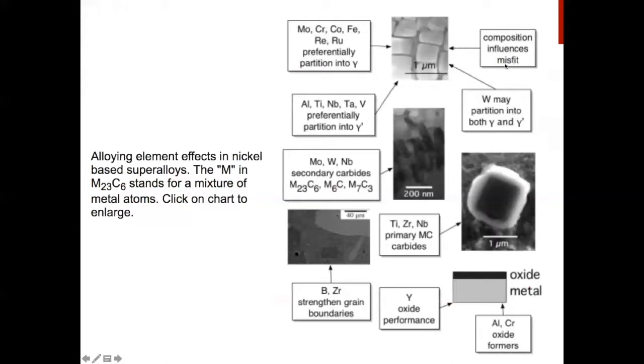Our composition strongly influences misfit. Tungsten can either partition into gamma or gamma prime, depending on what other elements are there, right? We have our gamma prime formers: aluminum, titanium, niobium, tantalum, vanadium, right? Our refractory elements are going to form secondary carbides like the M23C6 or M6C type carbides. Titanium, zirconium, and niobium can form MC-type carbides, right?